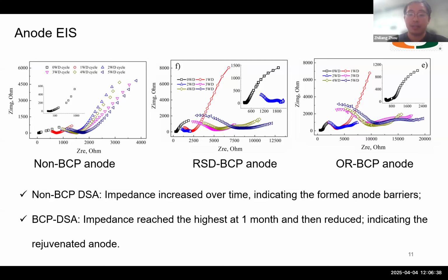This is because the electrolyte stored in the biochar can come out during the long term and dissolve the solid state barriers on the surfaces of the sacrificial anodes.